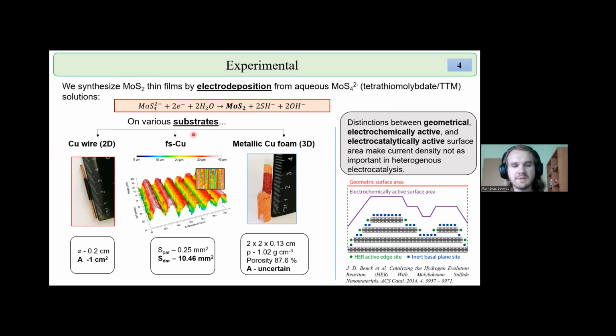Also, we use the femtosecond laser ablated copper foil surface. The surface is represented by this profilogram. And from profilometry, we know that while the projected surface area is 0.25 square millimeters, the developed surface area, that is to say the surface area that is measured by the incidence of light, is about 40 times higher. So this is a relatively very high surface area material. In addition, we tried deposition on electrodes with what is essentially an uncertain surface area, for example, these metallic copper foams. There's just no way to measure with simple measurements the surface area of this material.